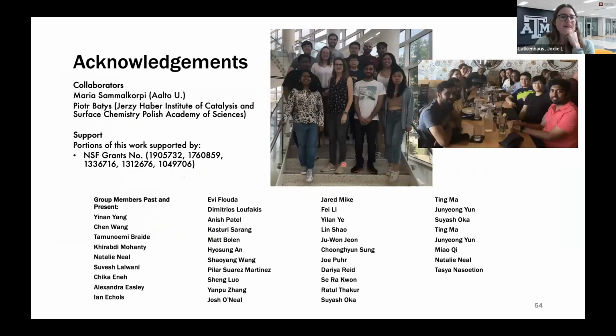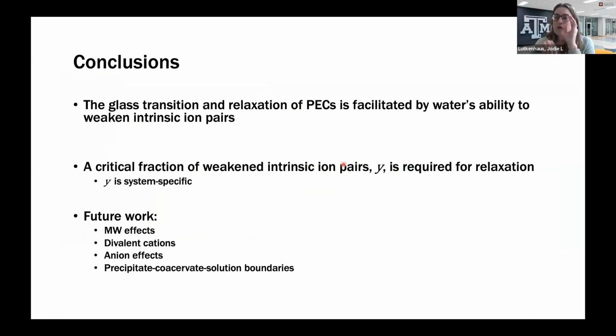Okay, so in conclusion, we are learning that the glass transition and relaxation of complexes is facilitated by water's ability, probably, to weaken or lubricate the intrinsic ion pair. We think there's a critical fraction of weakened intrinsic ion pairs required to go through that relaxation. And then our future work, there's so much future work, but here's a few things that we're thinking about: molecular weight effects, divalent ions, that's really interesting, anion effects, and then those boundaries.